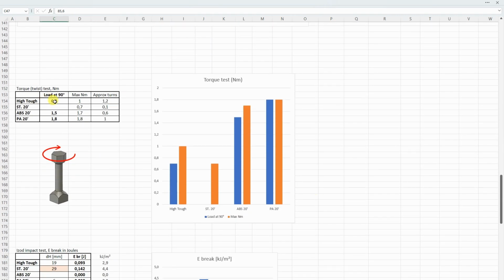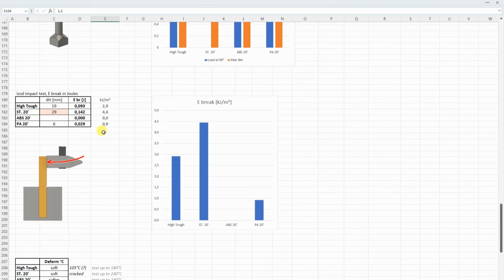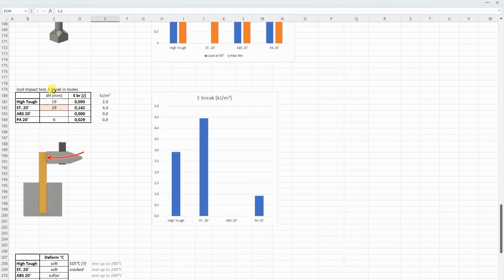Torque or twist test, again it was the weakest in this test, but very interesting information that I could make more than one turn until it completely failed. And the Izod impact test, well, high tough resin, I was expecting a better result here, but actually the rest of the resins, unfortunately I don't have that ABS 20 minutes cured version, but even the 2-minute version, I think it was stronger here.